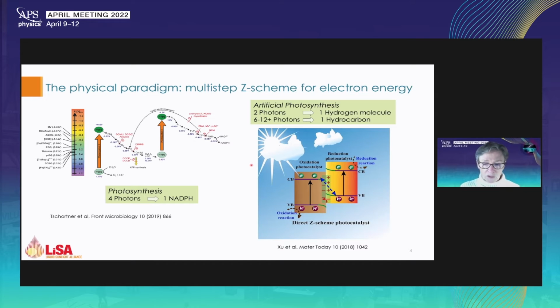So the paradigm for artificial photosynthesis is really quite similar. The idea is that you have an ability to promote electrons to an energy level that is suitable for driving the chemical reactions that you want. In the simplest embodiment, this is done by back-to-back semiconductors where light will be transmitted through them. You'll have a junction in the middle that will serve to create the fields that will split the charges, driving electrons over toward the reduction side over here, and the holes over to the oxidation side